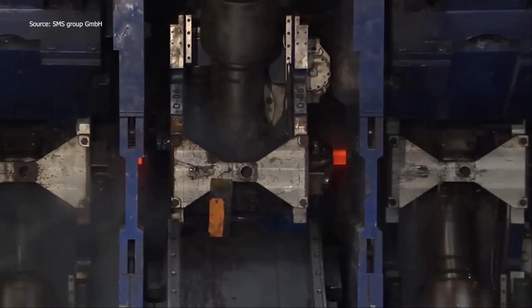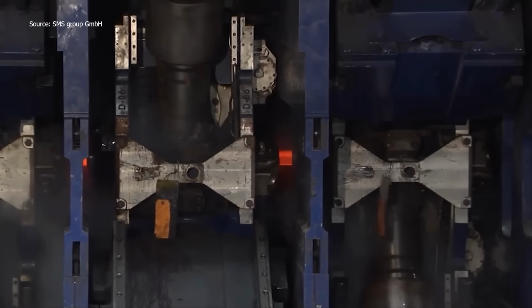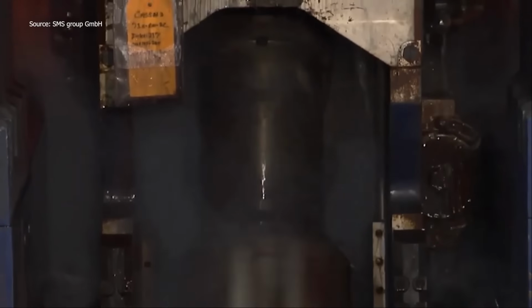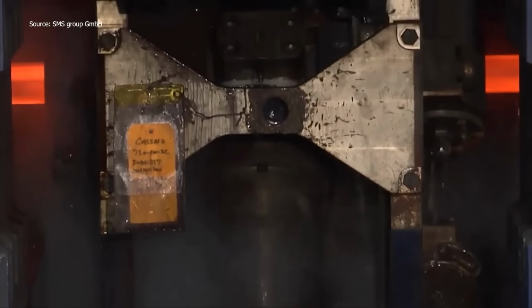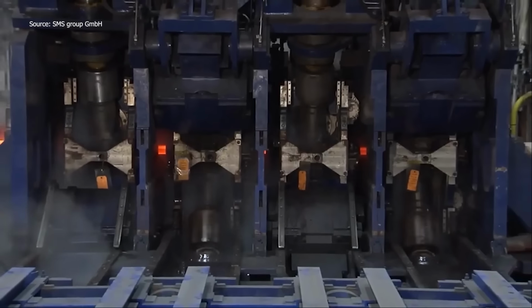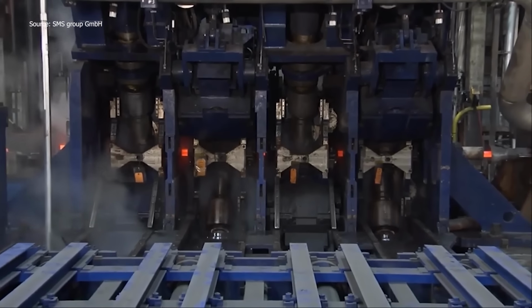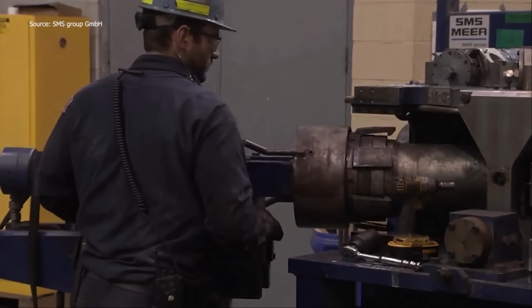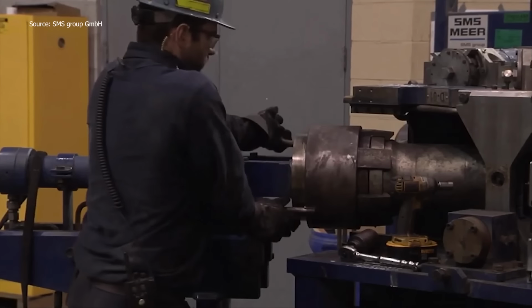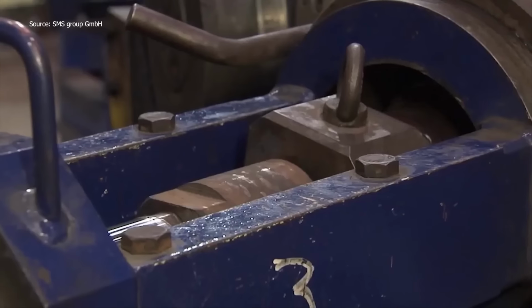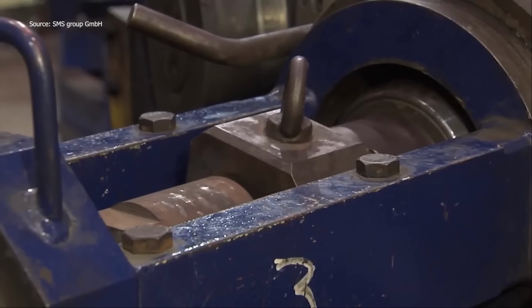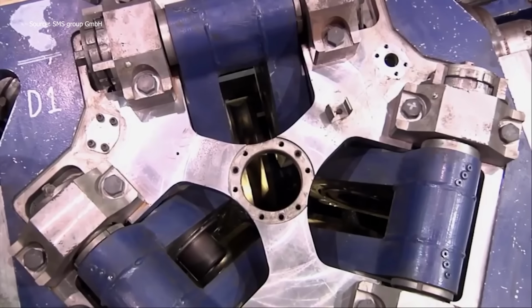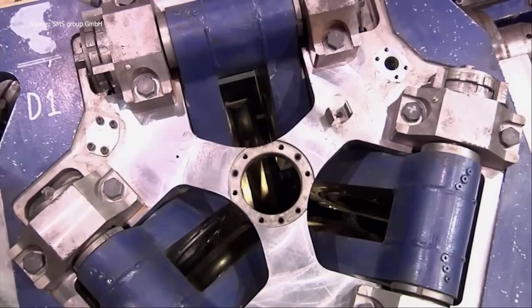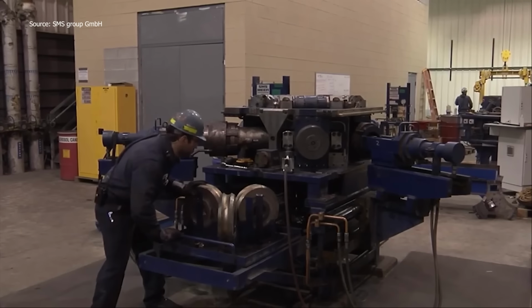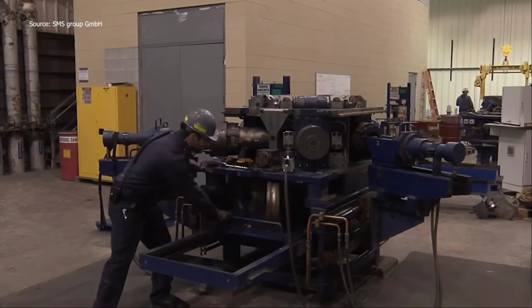The core of the upgraded line is the 3-roll precision sizing mill, PSM, delivering round bars at speeds up to 15 meters per second. The rolls are hydraulically adjusted under load and in real time. Calibration is automated, assisted by CCD cameras and real-time position measurement. The roll rings are inserted from below and clamped quickly into the cassette. All settings are fed to the automation system immediately after cassette change, removing human error.